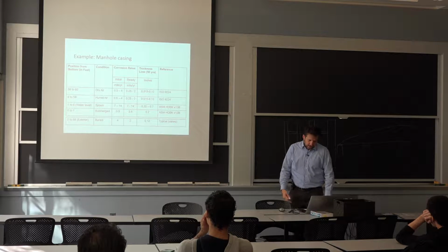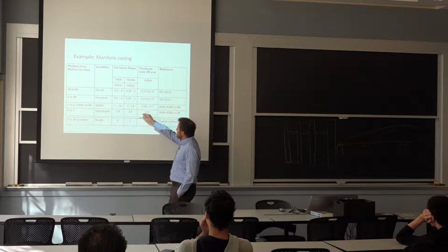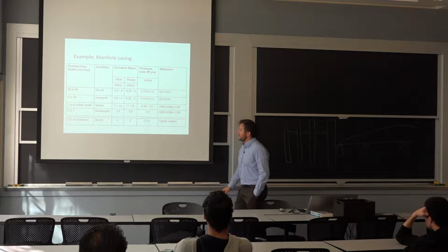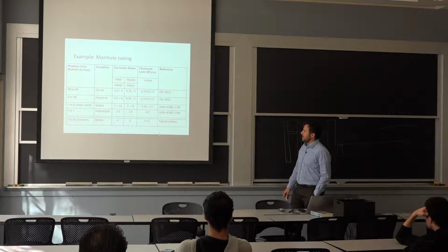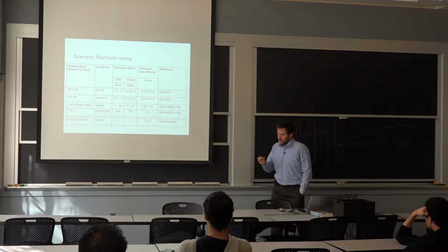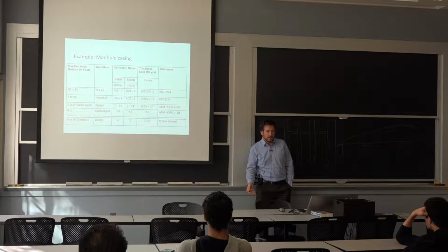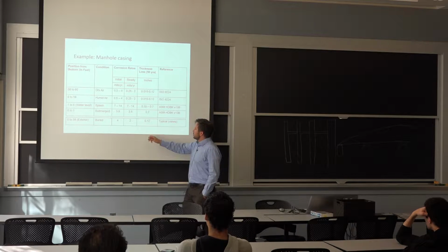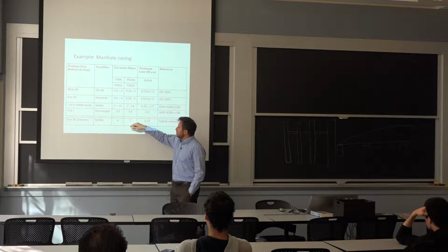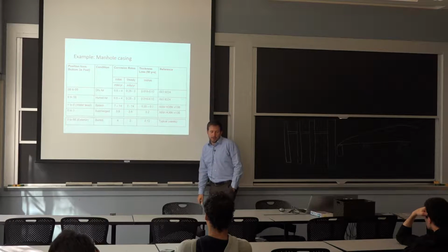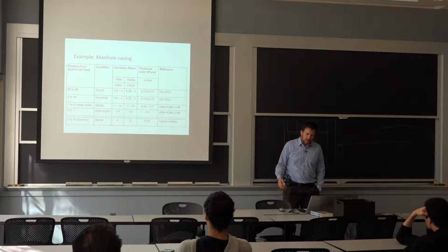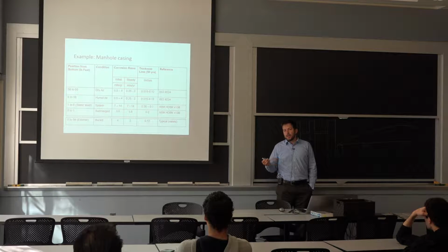So I'm showing this chart because you may be familiar with piers by the sea where the steel will corrode more rapidly. And a lot of times it's because of the exposure to submersion and then outside up in the air again. So you essentially are washing out a lot of the corrosion product, and therefore you have a bigger corrosion rate in these conditions. In the soil, a lot of times you're going to corrode at a smaller rate than in water. It has to do with pH. It's another issue with the supply of oxygen. So in soil, it will actually very much depend on the environment.